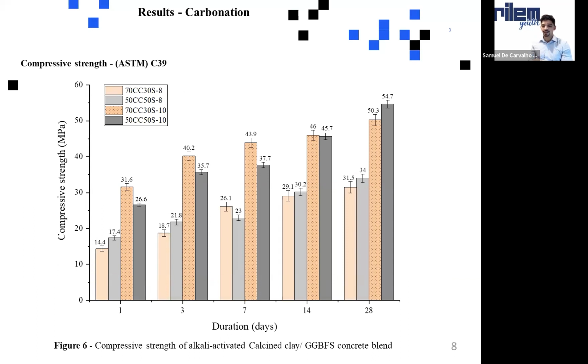As you can see here, at 28 days, we have all the mixes performing between 30 MPa and 54 MPa. As you can see, the higher alkali concentration of 10 had the highest compressive strength, something above 50 MPa. All the samples with 10% alkaline concentration had over 50 MPa. Either for the 70% of calcined clay or 50% of calcined clay, both performed very well and had a compressive strength over 50 MPa. However, the two mixes with only 8% of alkaline concentration had something around 30 MPa.